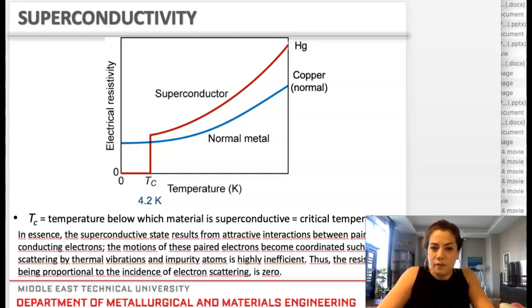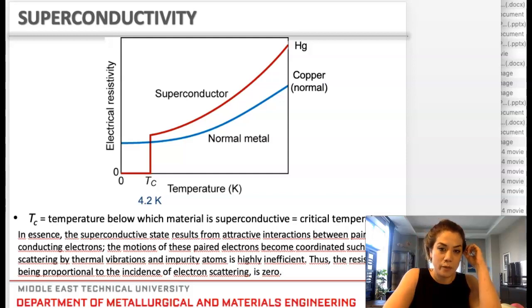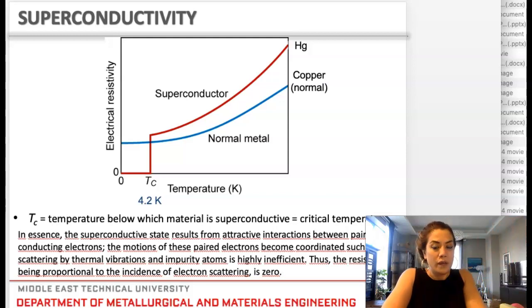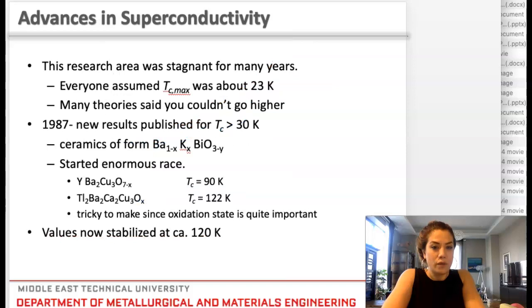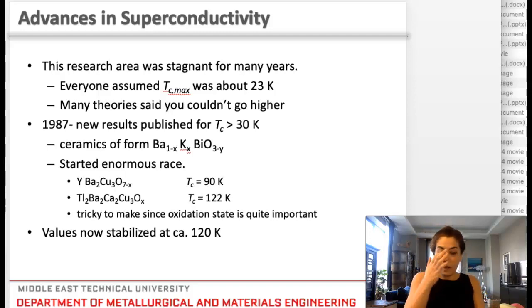So this was the main problem. Superconductivity is wonderful, but to get that property in the material, you need to go down to very low temperatures. So it is still a very large area to carry out research on. And I think a transition temperature as high as minus 70 degrees C was accomplished for superconductivity, but under extreme pressures, with hydrogen sulfide, I believe. But you have to apply extreme high pressures and cool it down to minus 70 degrees C.